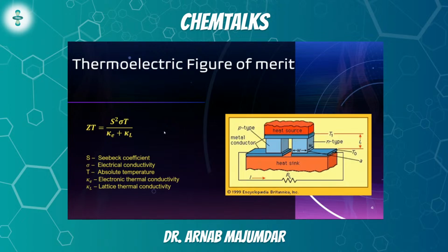Now, somebody can tell me that, okay, sure, but what about the temperature? We can increase the temperature as much as we want to. Yeah, sure, we can do that. But ideally, I would not want to run a device at 1000 degrees Celsius. I would want to run the device at 300 Kelvin, at room temperature. So we can see that with regards to the Seebeck coefficient S, the electrical conductivity sigma, the absolute temperature T, and the electronic thermal conductivity, that is kappa E, we can't do much about it. The only remaining parameter with which we can play quite a bit is kappa L, the lattice thermal conductivity. And that's what will form the crux of this talk. Okay?